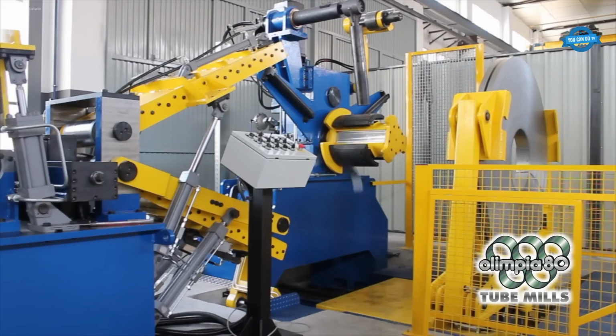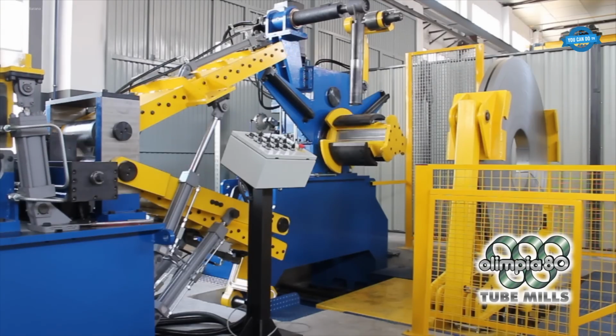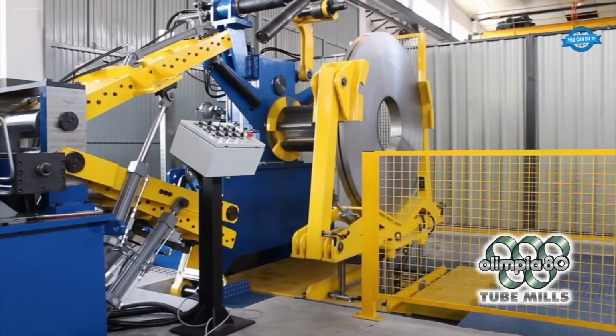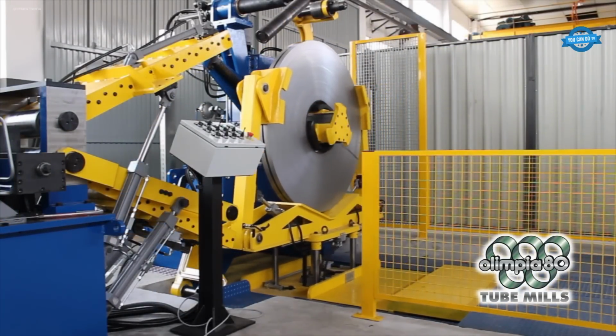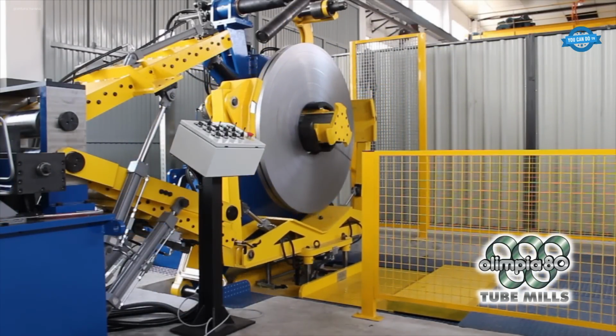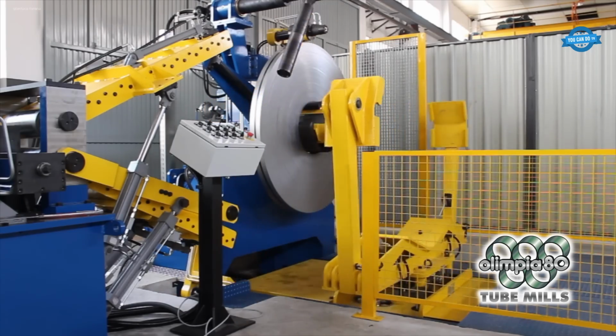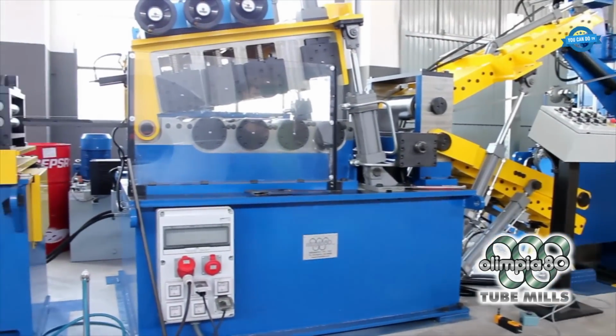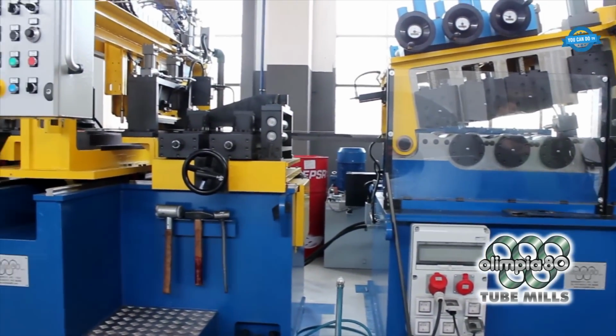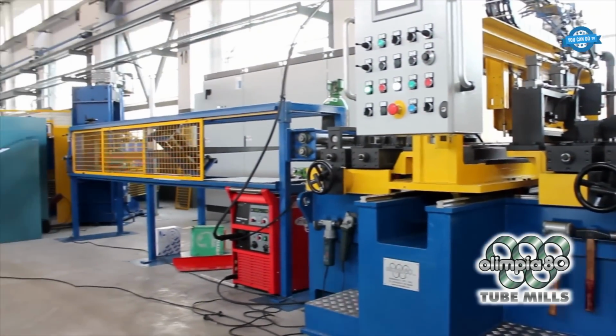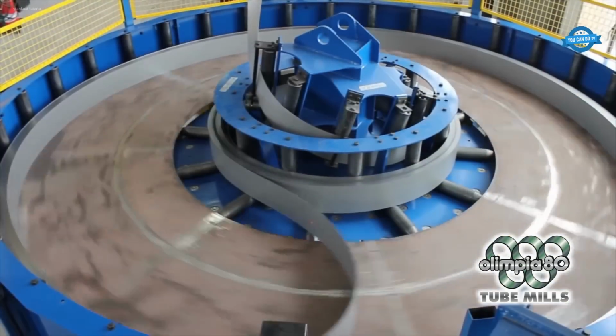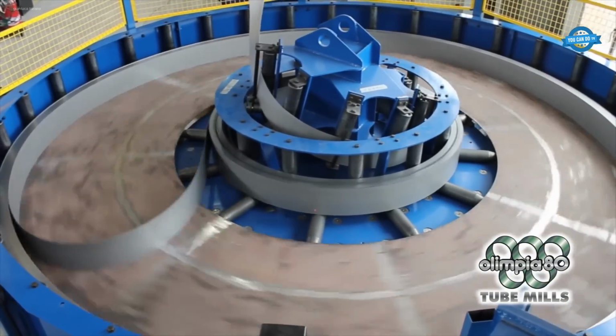The Olimpia 80HF linear cage forming tube mill is a fully automatic, high-performance system designed for producing carbon steel and stainless steel tubes using advanced linear cage forming technology. The model RCF 30-90 is capable of processing tubes with an outer diameter ranging from 30 mm to 88.9 mm, a maximum wall thickness of 4 mm, and production speeds up to 130 meters per minute.